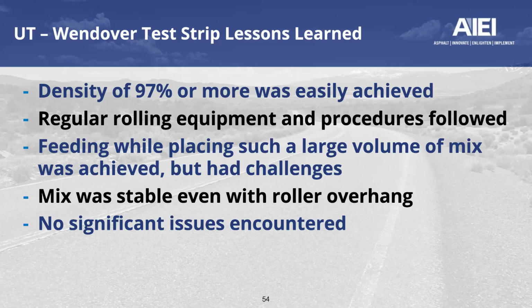What was most surprising to me about this test strip was the fact that you had unsupported edges. It was laid down at 7.5 inches loose, compacted down to 6. I truly expected this material to walk out some under the rollers, and it virtually did not. There was incredible stability with a double drum vibratory roller hanging over the edge about 4 to 6 inches without that material displaying any sloughing of it, even under vibration. So no significant issues were encountered in terms of densification.